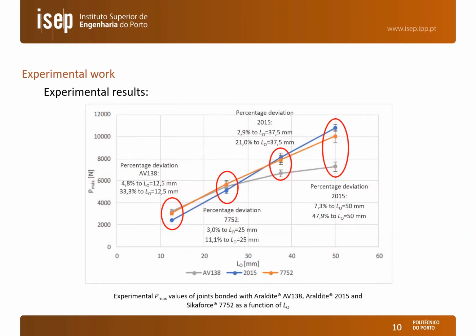In this figure we can see the maximum load as a function of the overlap length for the three adhesives. We can see that for the shortest overlap the AV138 and the 7752 behave best and very similarly. However, as we increase the overlap length, the 2015 and 7752 continue to increase the strength by a large amount, while the AV138 falls short of the other two adhesives. And this is because of the brittleness of this adhesive, as we are going to see in further slides in this presentation.